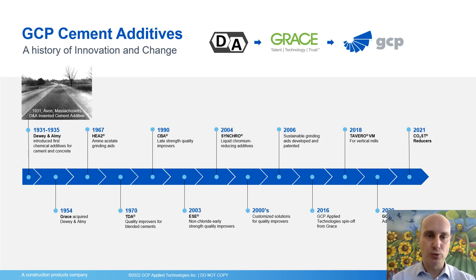The history dates back to the early 1930s when a company named Dewey & Almy was contacted by a concrete producer willing to produce a three-lane highway with a central passing high-speed lane of a different, darker color. The producer was looking to introduce carbon black in the mix design but was facing a rheological issue. Dewey & Almy eventually developed and introduced a technology of dispersants, notably lignosulfonate, that enabled the producer to homogeneously disperse the carbon black, and at the same time improve the rheology and reduce the water demand of concrete.